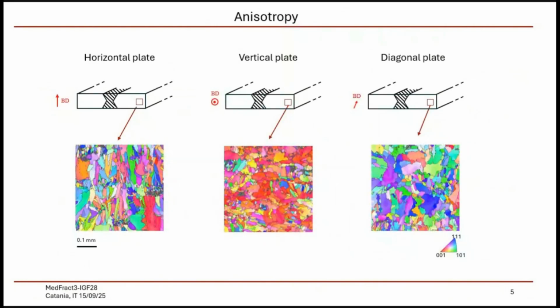Something important to mention, why it's important also to consider the building orientation, is because laser powder bed fusion and other processes induce anisotropy at a microscopic level in the components. Here you can see EBSD analyses that were performed on the cross sections of the plates, far enough from the BOPs to avoid any effect of the welding process. And you see in the horizontal plate, we have columnar grains, elongated grains growing along the building orientation, quite long, while in the vertical plate, we have a more homogeneous distribution, and most of the grains are color-coded with red, corresponding to the 001 orientation. And then the diagonal plate has a situation which is halfway between the horizontal and the vertical plate.